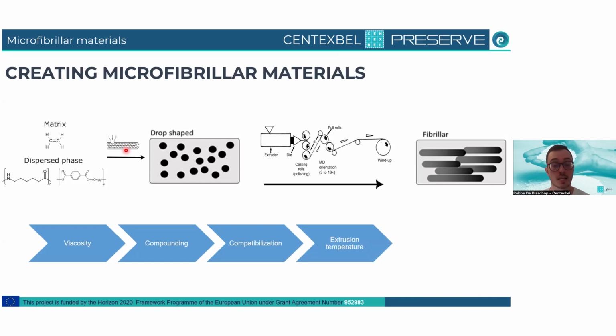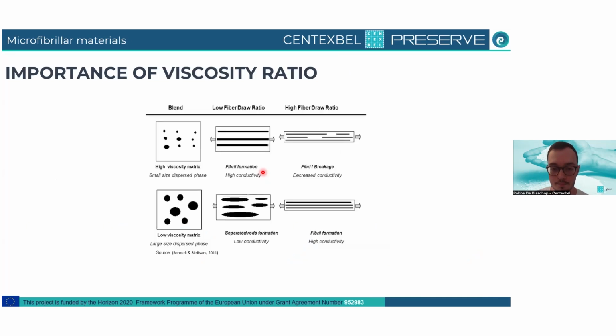Then next is the extrusion temperature. I talked a little bit about this during compounding, but also during the extrusion. The temperature we will be using is very important during the process, as the polyethylene and the PET have a very different melting temperature. And then last of all, the cast film extrusion, the roll temperature, the speed, the stretching during the extrusion is also very important to create these fibrils.